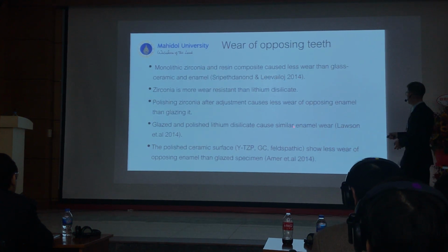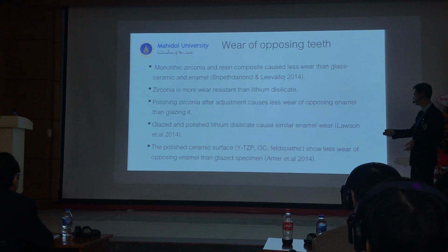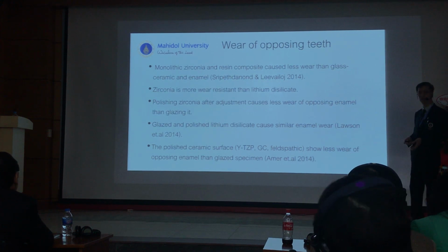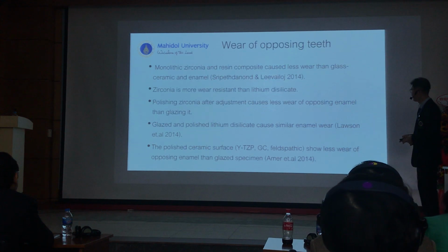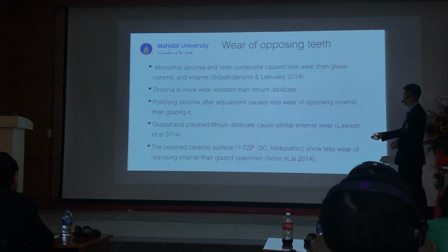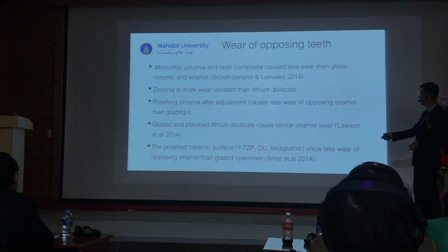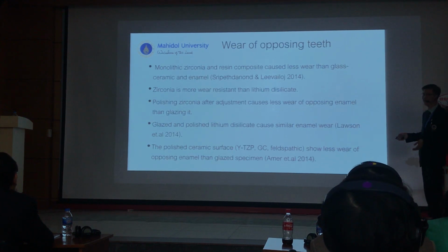Glaze sometimes is just enough, and sometimes it's worse than just polishing. Polish is always better if you consider wear. It's going to cause less wear than glazing or firing again in the furnace. So polished zirconia, Emax or plastic show less wear of the opposing dentition compared to glazed specimens. A lot of studies about that.